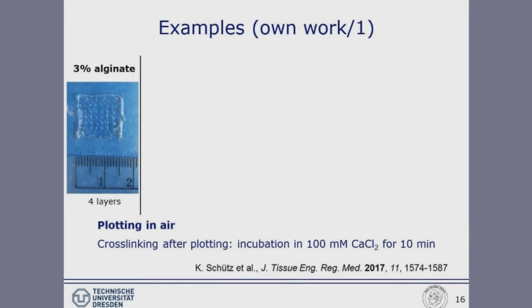Example from our lab, we again used alginate as the base material, again 3% as a maybe common concentration. But what you can see from this photograph here, taken from only a 4-layered scaffold, is that the shape fidelity is really not very good. The pores, which should be rectangular, already after 4 layers start to become roundish. So this is a bio-ink which definitely is not suitable for macroscopic constructs.